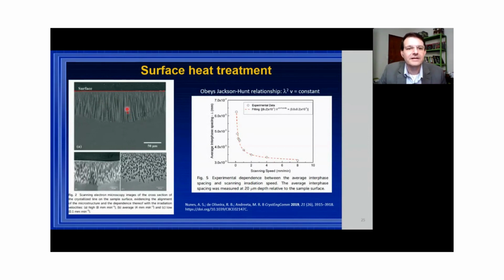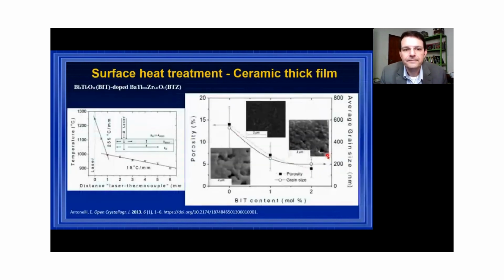We have a very aligned microstructure with the two phases. And when you decrease the speed, it becomes disorganized, okay? And the average space between the phases follows the Jackson-Hunt relation. So it's really a eutectic material.